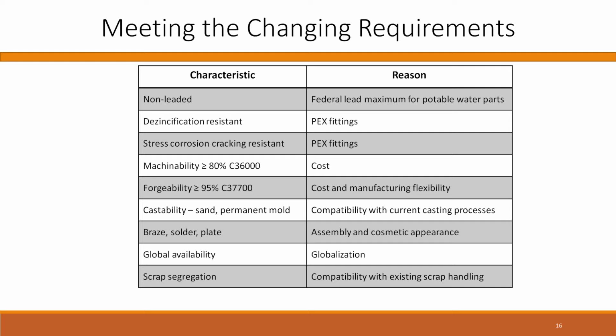To reduce costs, there's a certain minimum amount of machinability that these alloys have to meet, or a certain minimum amount of being able to forge it, like alloy 377, or they've got to cast it. And the alloy has to be compatible with the sand or permanent mold or die casting processes that are currently being used. For parts that are brazed or soldered or plated, the alloy can't have something in there that compromises those capabilities. The alloy should be globally available, and preferably when it comes to scrap segregation, you'd like to mix everything together. But some of these alloys require their own segregated scrap stream to get a minimum of contamination at the mill when they want to take this material and melt it to make new rod. So that's the metallurgy presentation.